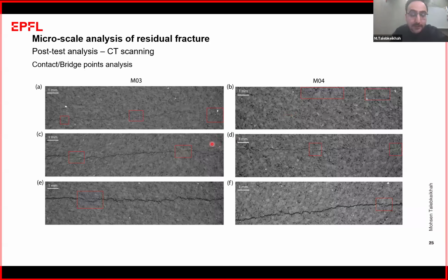And here you can see that as we get close to the tip of the fracture, we see some unfractured and bridge points. For example, here the fracture completely disappeared, or here the fracture is not connected. Also here the fracture is not connected. Here the fracture disappeared. Here it is connected, but it is lower than the resolution of the CT scan image, so we assumed it as a contact point, not as a bridge point.